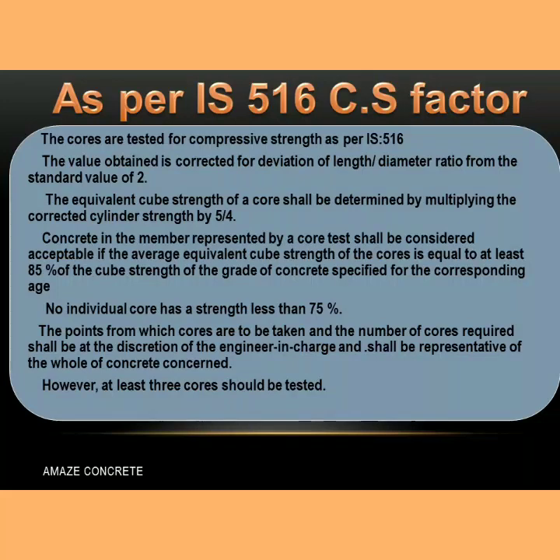As per IS 516, the value obtained is corrected for deviation of length by diameter ratio from the standard value of 2. The equivalent cube strength of a core shall be determined by multiplying the corrected cylinder strength by 5/4. Concrete in the member represented by a core test shall be considered acceptable if the average equivalent cube strength of the cores is equal to at least 85% of the cube strength of the grade of concrete specified for the corresponding age, and no individual core has a strength less than 75%. The points from which cores are to be taken and the number of cores required shall be at the discretion of the engineer-in-charge and shall be representative of the whole of concrete concerned. However, at least 3 cores should be tested.